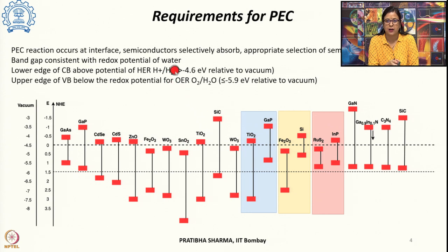So, it should be higher than minus 4.6 electron volt, which is relative to the vacuum level. At the same time, the upper edge of the valence band should be below the redox potential for the oxygen evolution reaction, which corresponds to minus 5.9 electron volt. Now, if we see both the conditions, such that the conduction band lies above this and the edge of the valence band lies below this, is satisfied by very few materials,